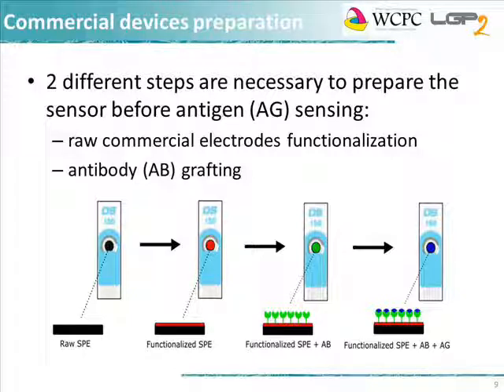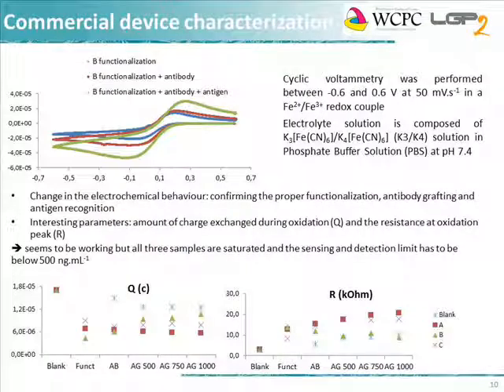The prepared sensor was tried against 3 different concentrations of antigen, ranging from 500 nanograms per milliliter to 1000 nanograms per milliliter. For each step, the system is then analyzed using the CV tool that I presented to you before. I took here the example of the functionalization agent B. The change of electrochemical behavior of the surface of the screen printing electrodes can be seen on the graph, especially on the oxidation peak.